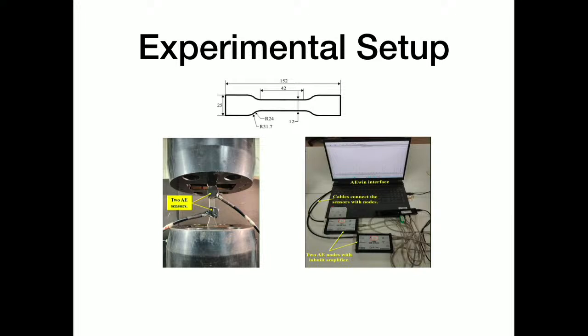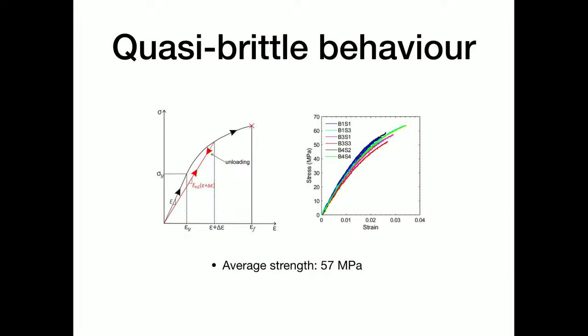This is the experimental setup where we have the dog bone specimen that you can see here. It's an epoxy dog bone specimen. There are 2 AE sensors and the required paraphernalia to acquire AE data. We observe this kind of stress strain response, and average strength is around 57 MPa. This is what we are modeling.